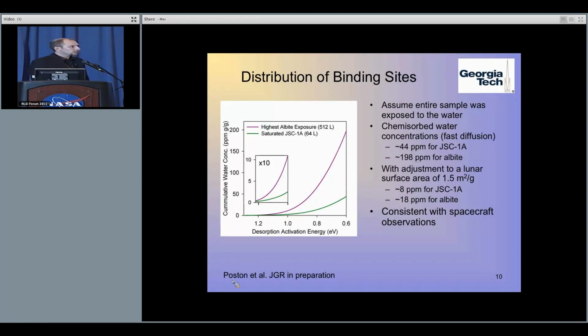Right, so then what I have plotted here is I took these temperature programmed desorption data for the saturating pressure or exposures, and I converted that to a concentration versus the desorption activation energy, the energy you have to give the water to desorb. And I plotted this cumulatively from highest energy to lowest energy.